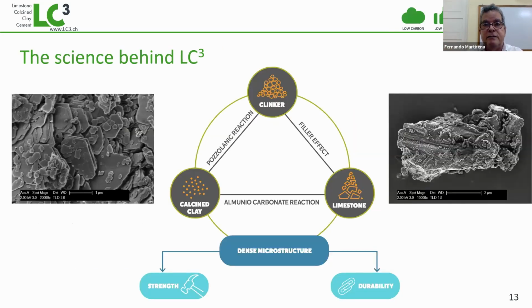I will not give too many details, not to bore the audience, because everything is already published in the public domain. But we have three reactions taking place at the same time. First, the pozzolanic reaction, which is normal, well-known, between clinker phases and calcined clay. Also, we see a dilution effect of clinker by the filler effect caused by the limestone. It's also well-known, well-described elsewhere. And the new thing here is that we have a synergy between calcined clay, the alumina available in calcined clay, and the carbonates available in the limestone to produce new reaction products that contribute to a denser microstructure, thus reflecting in a higher strength and a higher durability of the system. That's the basis behind all of this development.